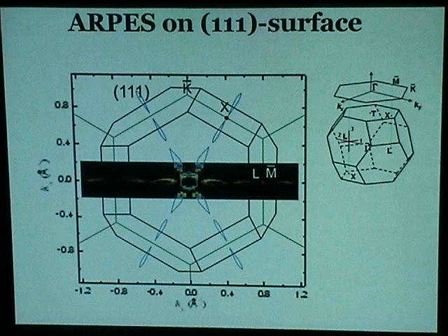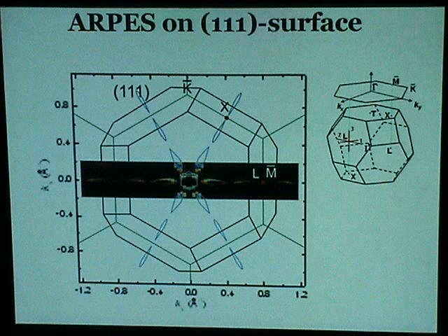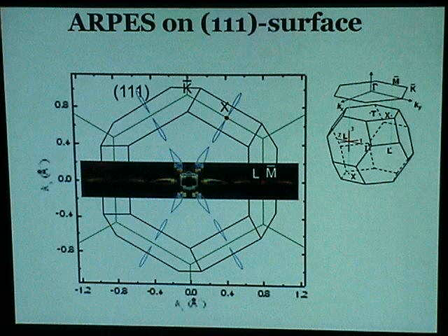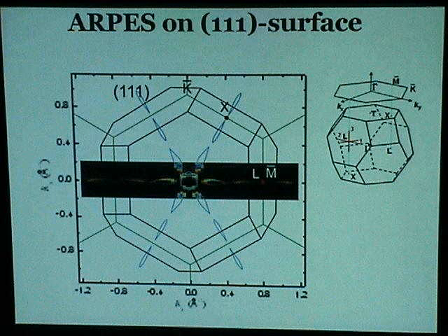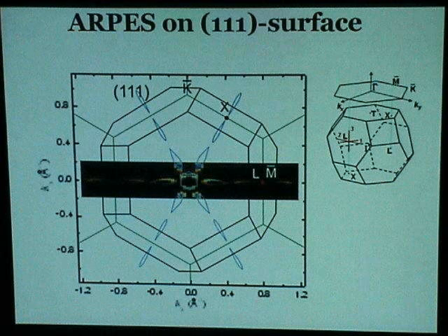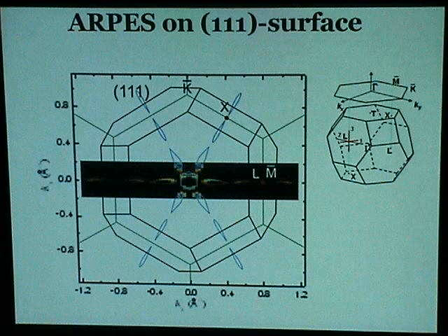So if we cleave the 111 surface, right away we can get a surface state, very clear. And you have a large Luttinger volume here, so it's much larger than the carrier concentration in bismuth, so you know right away it cannot be bulk representative. So this Fermi surface is a surface state. But I need a critical check. Just as in sodium cobalt oxide, where we did systematic work to find out what is the surface effect and what is the bulk effect, in this case we did a similar check.